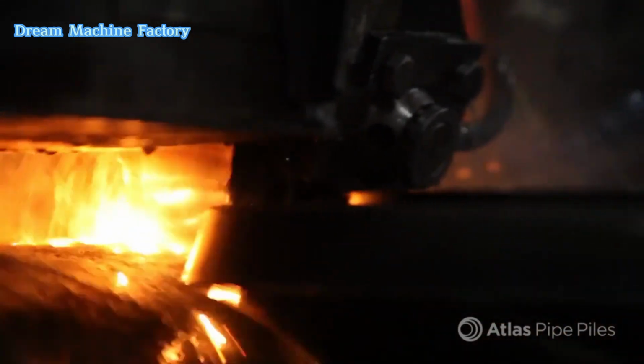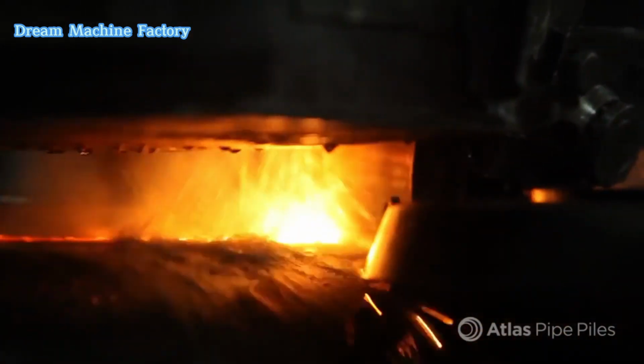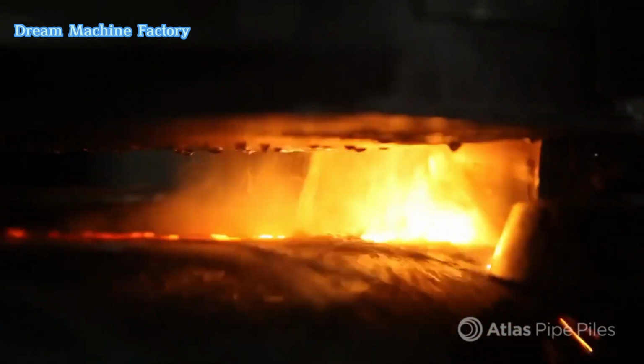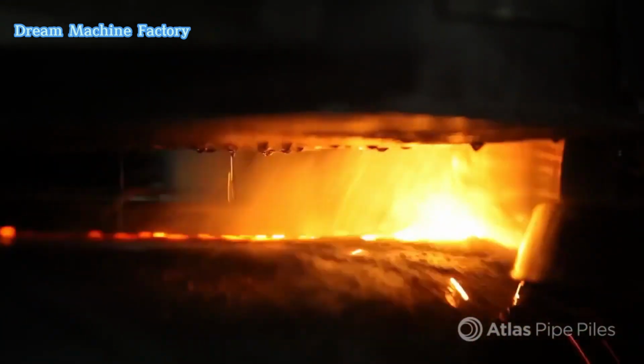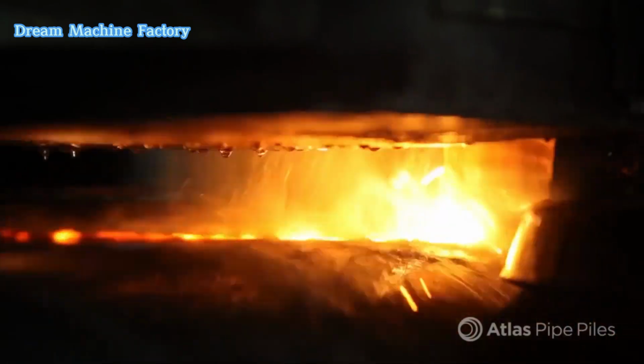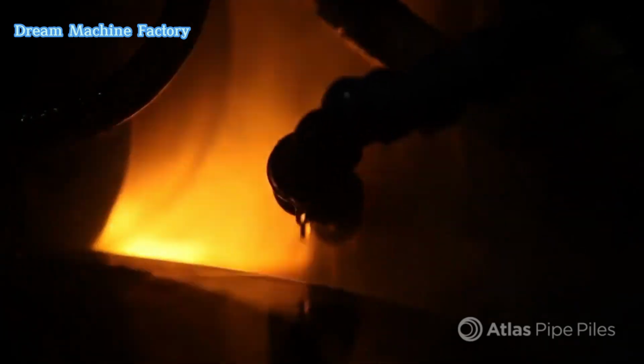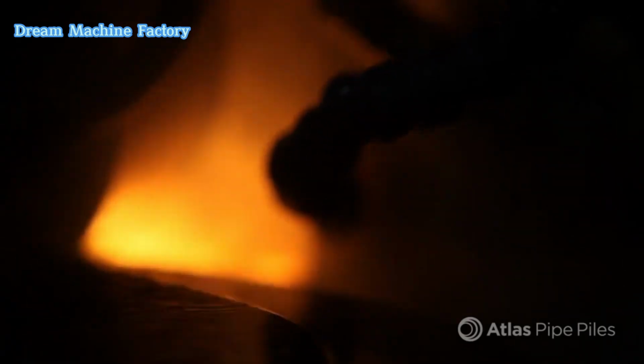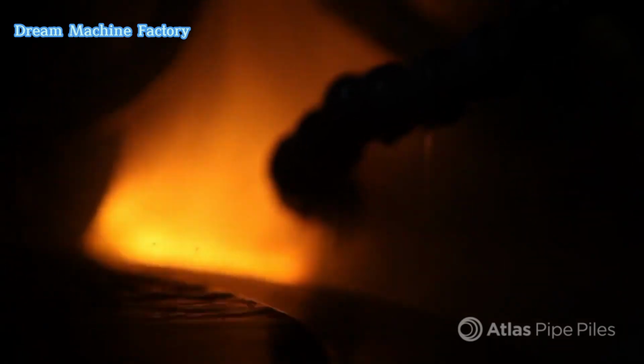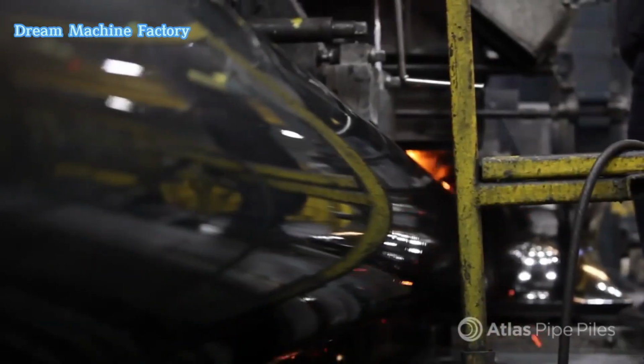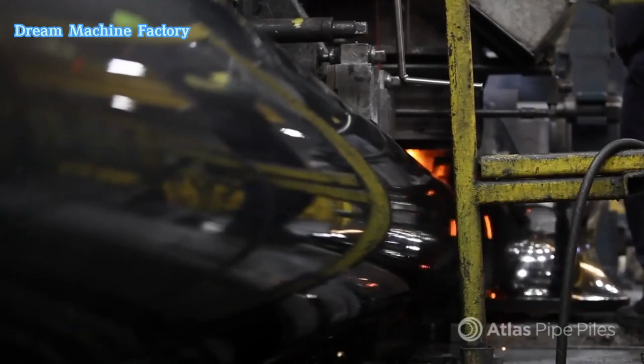The U-shaped steel strip proceeds to the welding stage, where the edges are joined using the electric resistance welding (ERW) technique. This method employs two copper contact shoes to pass an electrical current through the edges of the steel strip. The resistance to the electrical flow generates heat, raising the temperature in the weld zone to approximately 2,700 degrees Fahrenheit.